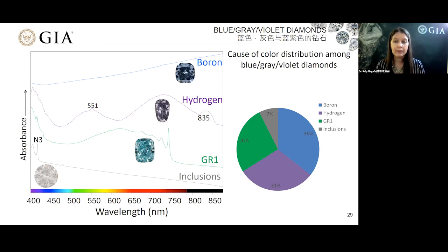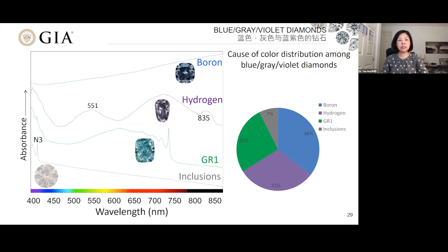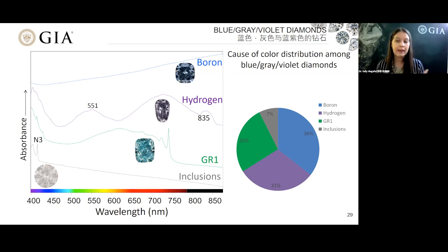The absorption spectrum is relatively featureless across the visible range. What we're seeing here is a tail of an absorption feature that occurs within the infrared, and then it slopes down into the red, leaving a transmission window within the blue. 就是第一条谱线，您可以看它其实没什么特点，整个就是一条线，但是它越往右走的话，它是上扬的，所以红区甚至红外区这边都是完全吸收的，然后留下谷底的地方是在蓝区，所以钻石显蓝色。Below that are diamonds colored by hydrogen-related defects. We discussed these earlier in relation to green diamonds, but depending on how the bands have shifted, we can also see a blue, gray, or violet color.